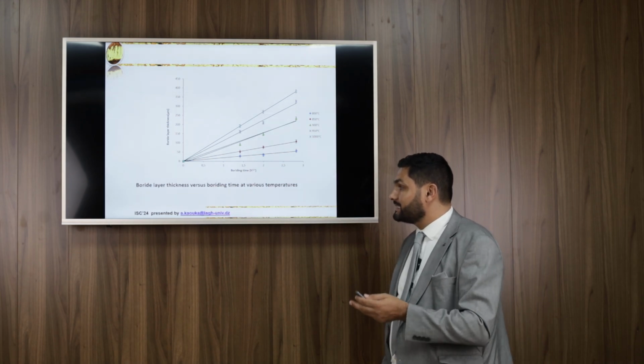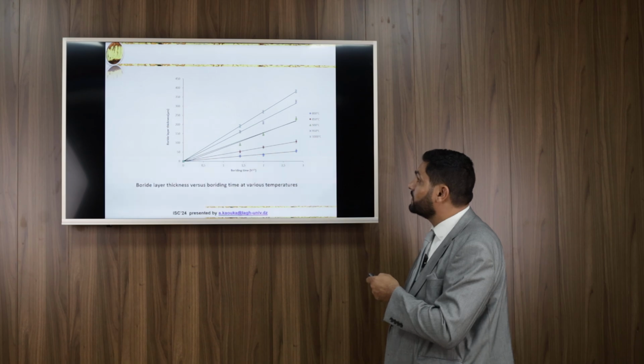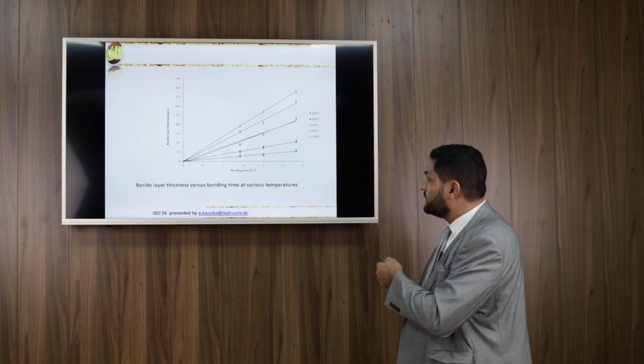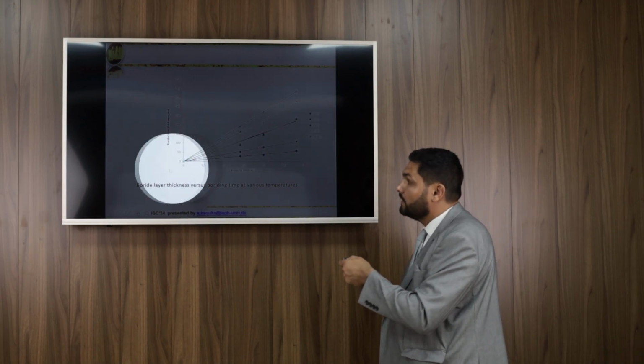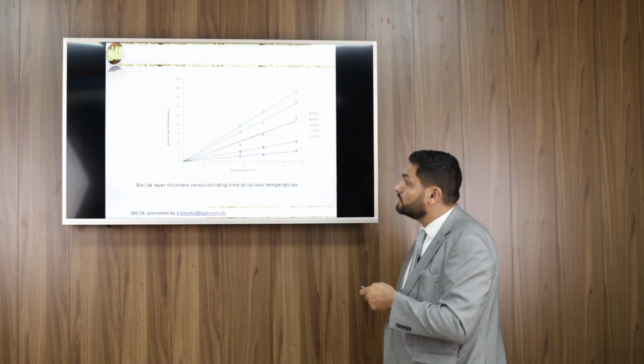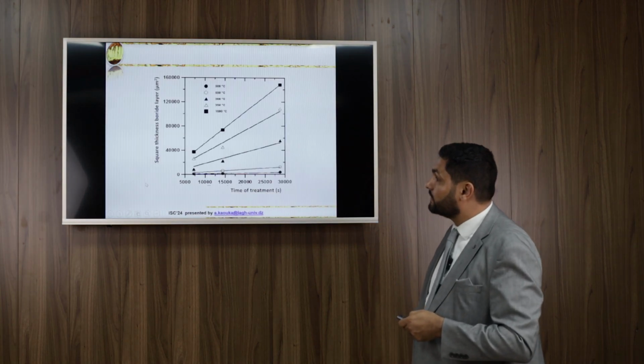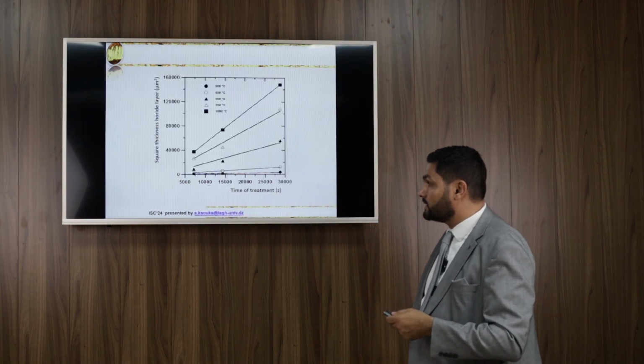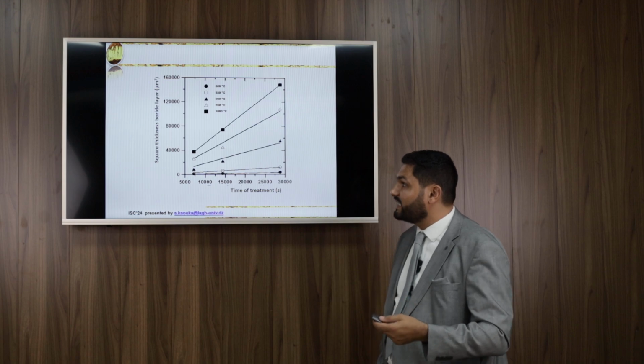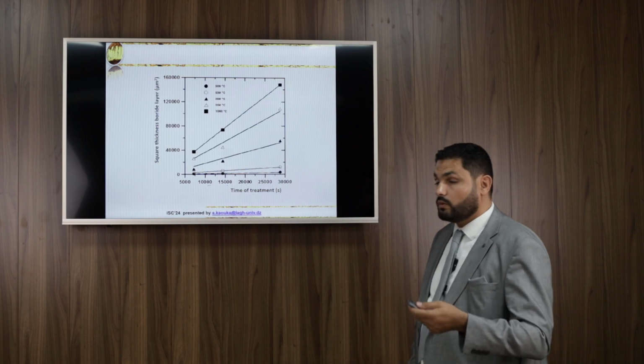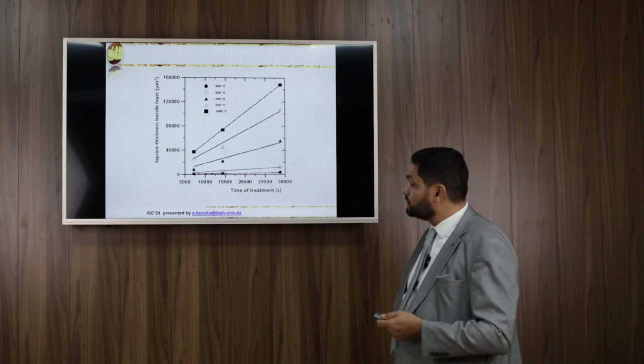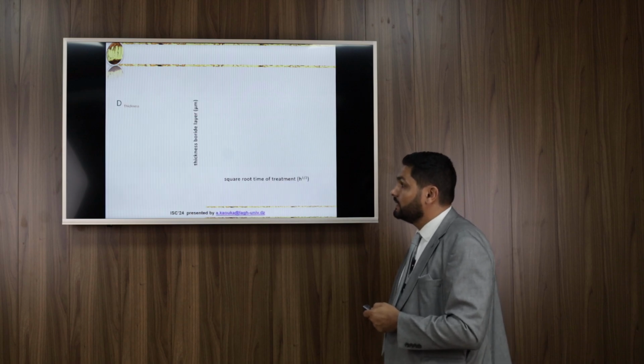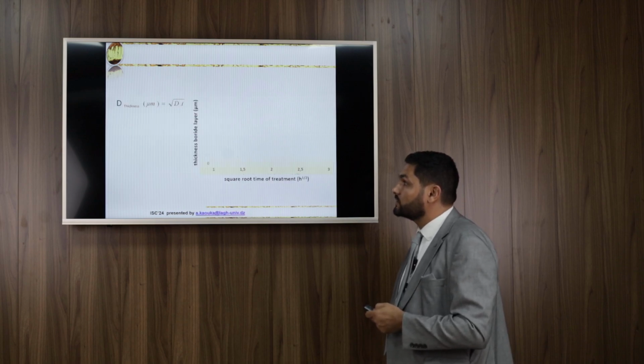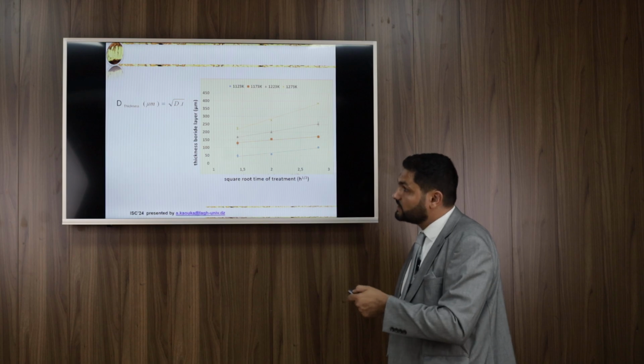versus boriding time at various temperatures, 800 to 1000 degrees Celsius. We have a linear curve with boriding time, and also we try to measure the square of the thickness of boride layers as a function of time of treatment. And the thickness of boride layers can be calculated with this relation.